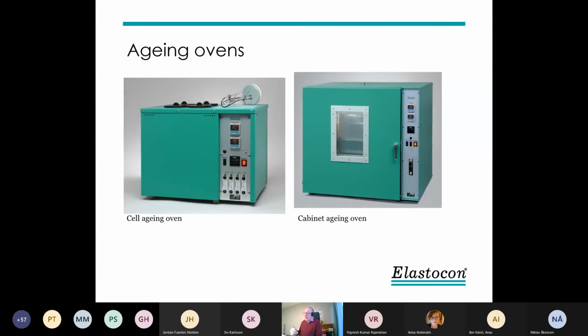We designed a couple of ovens. Originally, for rubber testing, cell ovens were very common and described in the standard. And the cells here are 100 millimeter in diameter and 300 millimeter high. And you see the test specimen holder lying on the top of the oven. There is also an air pump which feeds air of the specified amount of 3 to 10 changes per hour into each cell.